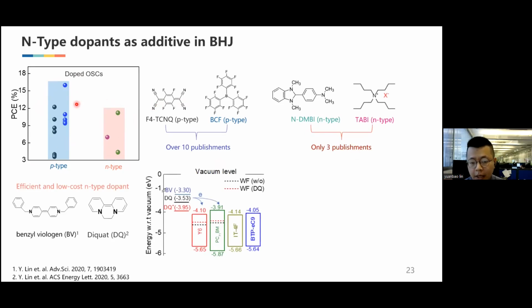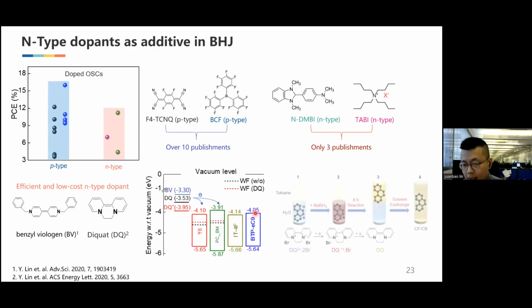This is because the energy level of the n-type dopant is very high, so it's very easy to oxidize if we expose it to the air. So we tried to synthesize some other efficient and low-cost n-type dopants. From the energy level angle, these two dopants can transfer electrons to the acceptors. And the synthesis process is very easy compared to the material synthesis. It only takes 1 day to synthesize this material.